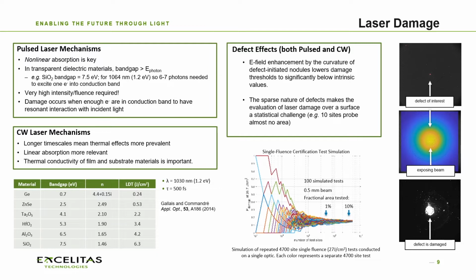So the band gap of the material is key. The band gap, as it happens, relates also to the refractive index. And so there is a very well-defined relationship between the refractive index of the material and the laser damage threshold of a given material. And that has a fairly significant impact sometimes on the thin film design space that we can work with when we're designing coatings for pulse laser damage mechanisms.